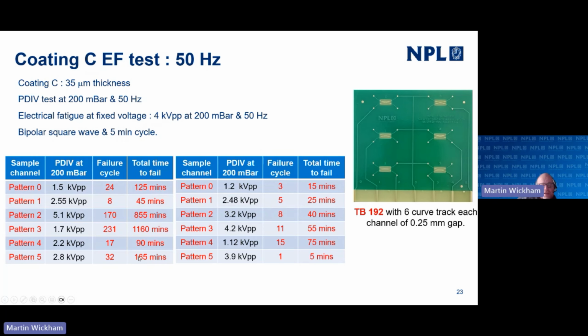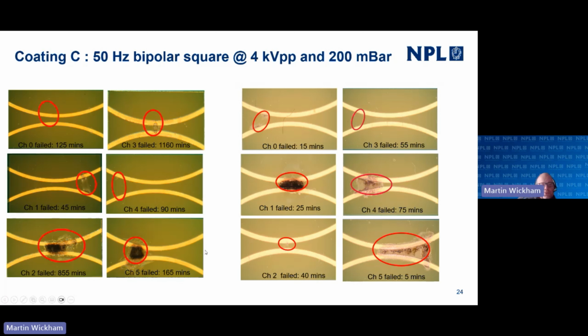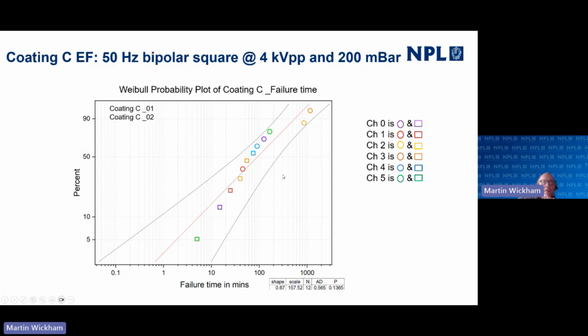And again, you can see these failures occurring. Again, for some of these, 5.1, the inception voltage is above 4.2, not by much, but at least one is above the electrical fatigue voltage. Again, this is a test vehicle with just curved tracks on, but you can see that the failures again are occurring at areas where potentially the field strength isn't the highest.